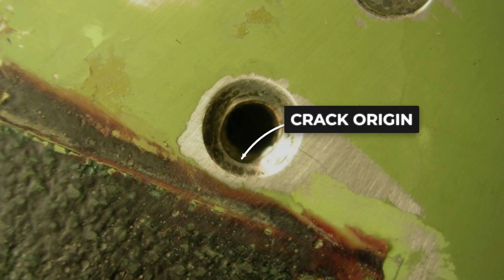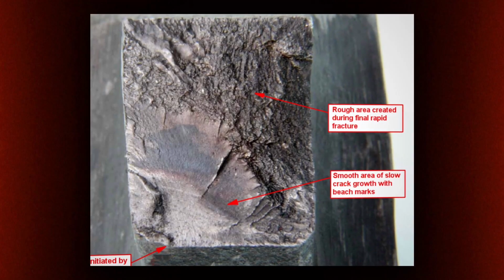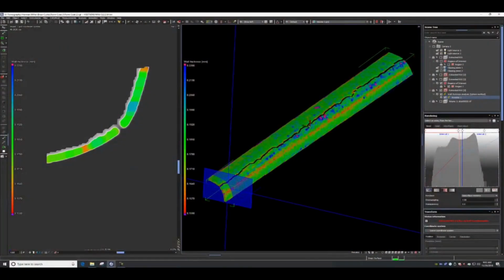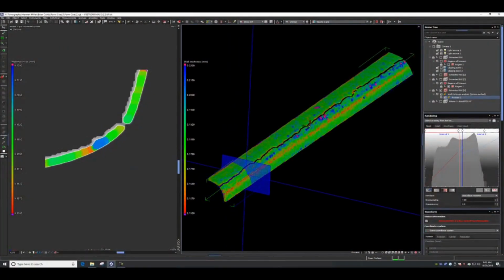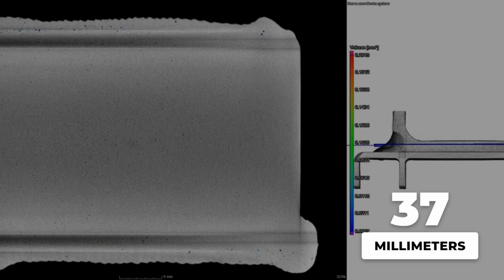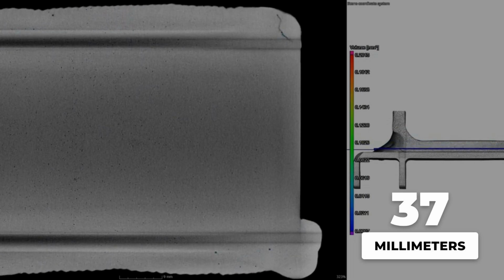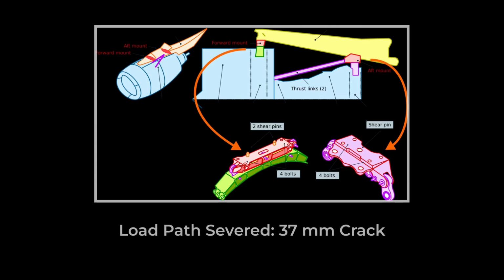Beach marks, like ripples on a pond, radiated outward from a fastener hole near the upper aft edge. Each mark recorded another cycle of stress. Another day the part survived before giving way. CT scans sliced through the fitting's cross-section, revealing the crack's true reach: 37 millimeters from origin to rupture, enough to sever the load path between engine and wing.